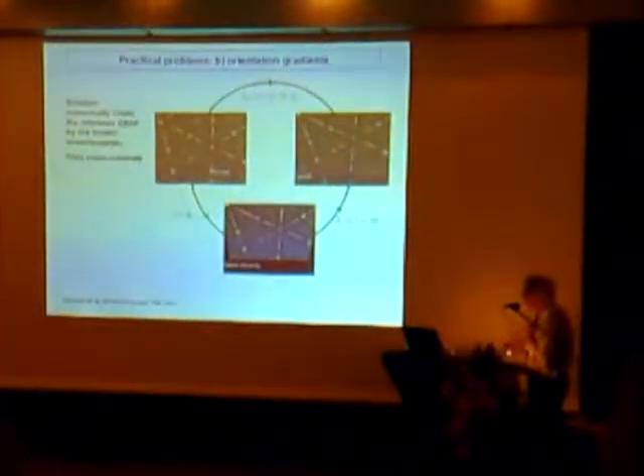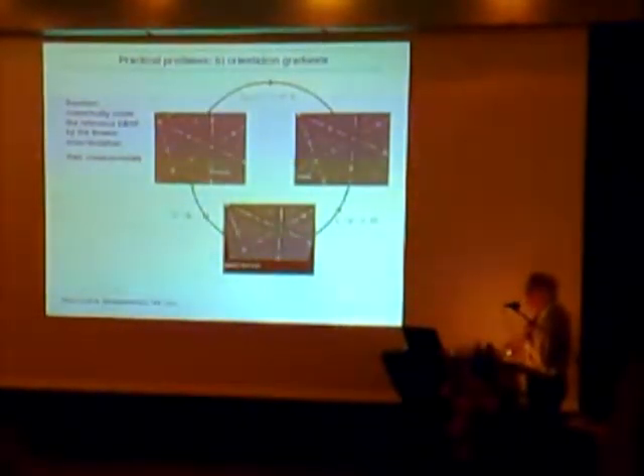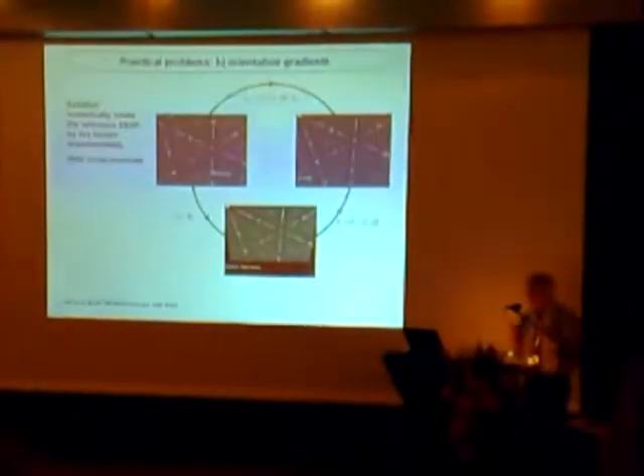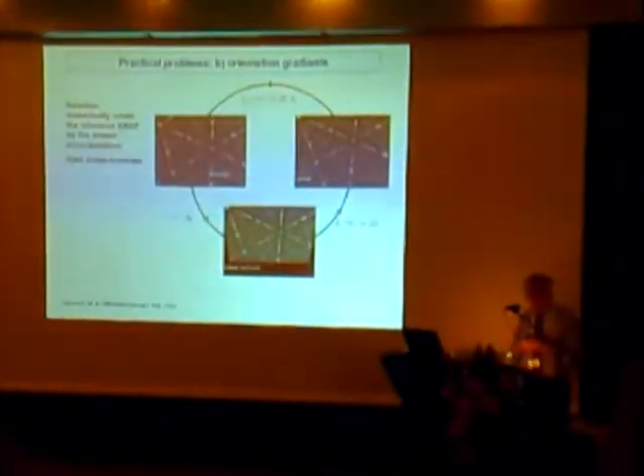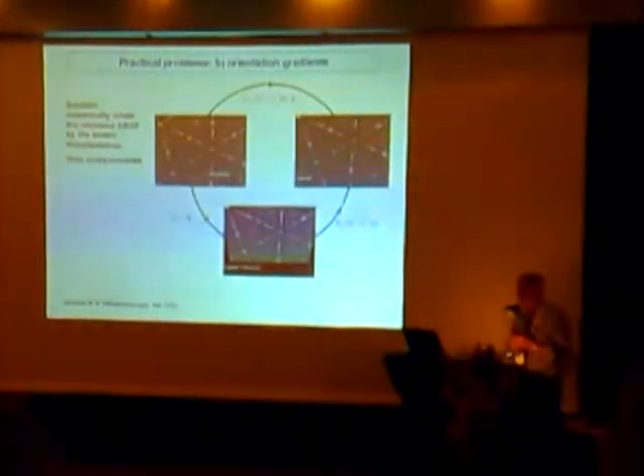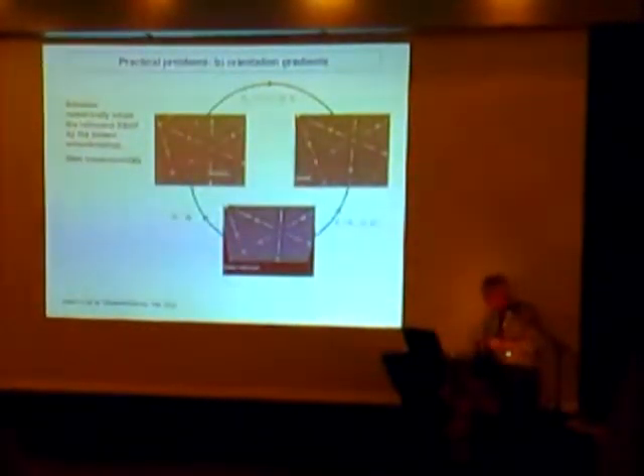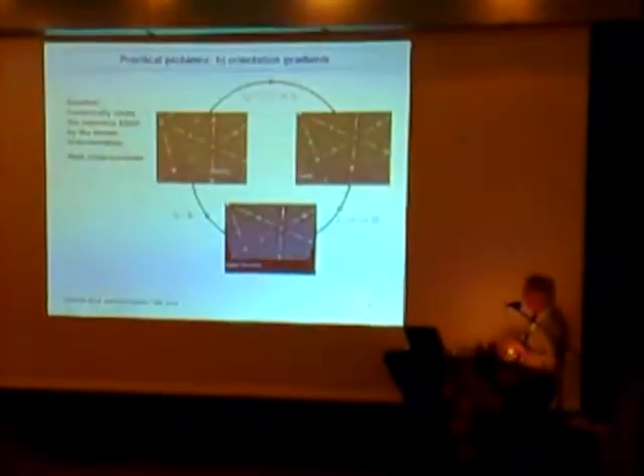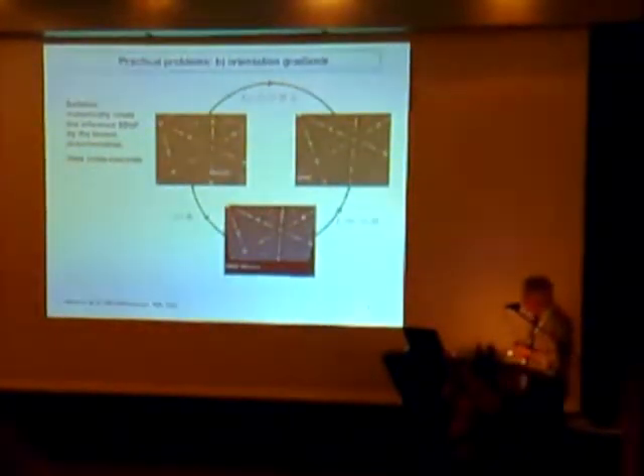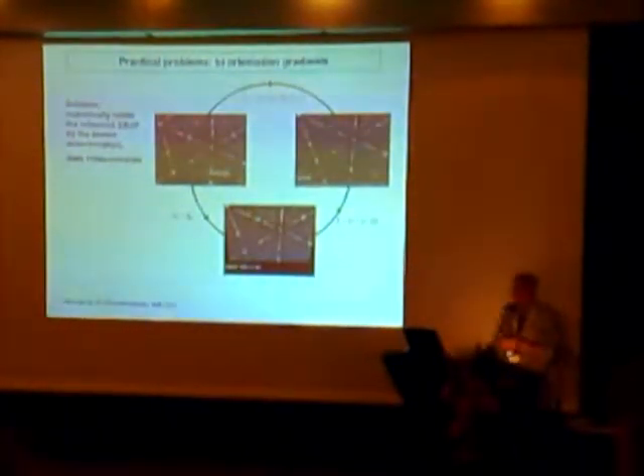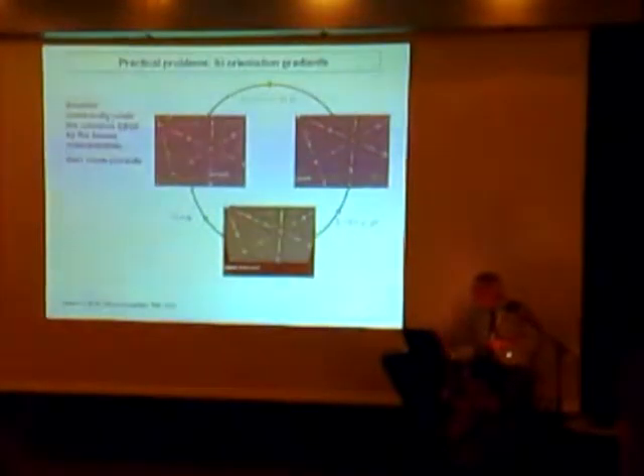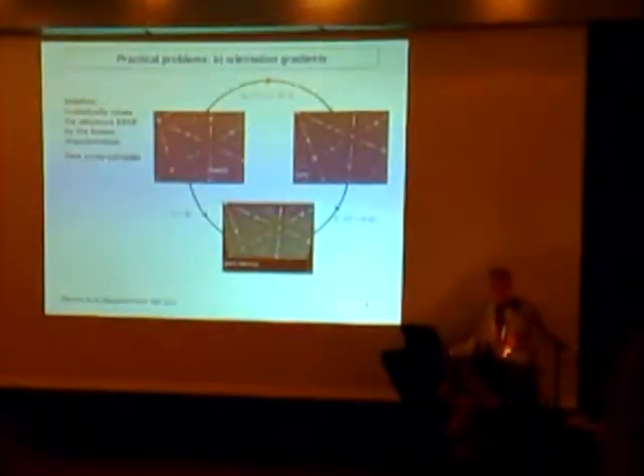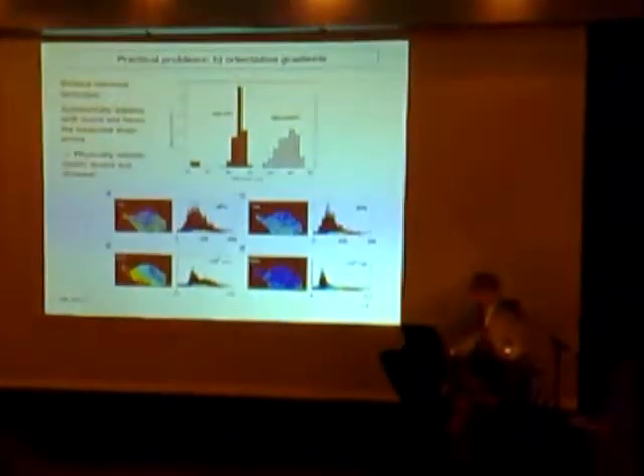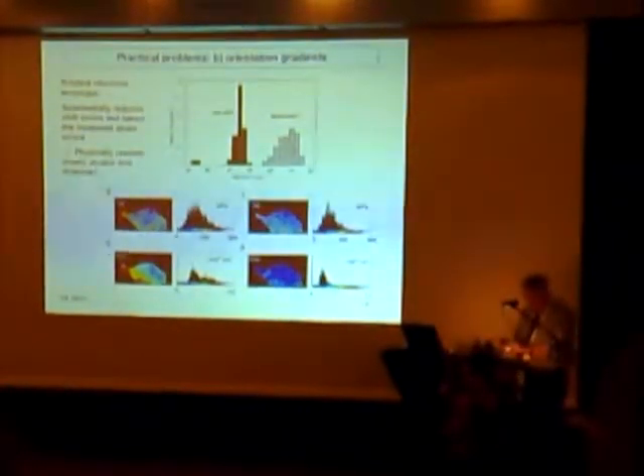Then you compare the rotated reference to the current pattern using cross correlation. And this will give you misorientations and lattice strains to a really high degree of accuracy. This, in fact, was published earlier this year, so it's quite a new development. We call this the rotated reference technique. And this is an example.